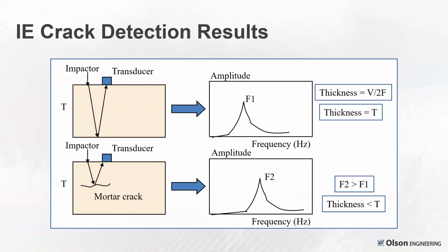So what we found on the project was we would get echo peaks where the thickness equals this factored velocity divided by twice the frequency. When it was thicker, we would get the normal thickness. And if there was a mortar crack separation in that vertical collar joint, we would get a higher frequency, which is a shallower thickness echo. So we were getting evaluation of the continuity and contact conditions of the lime mortar in the joints of this 2 foot thick masonry wall.